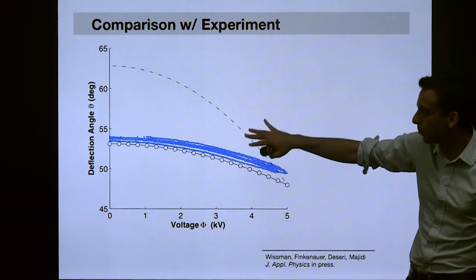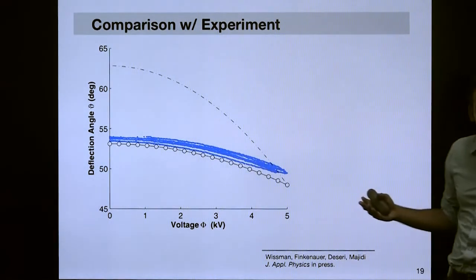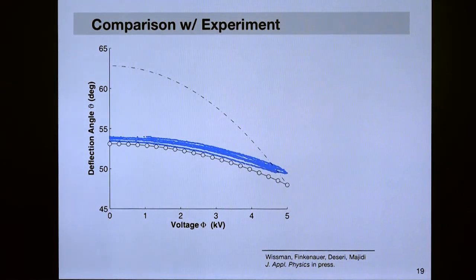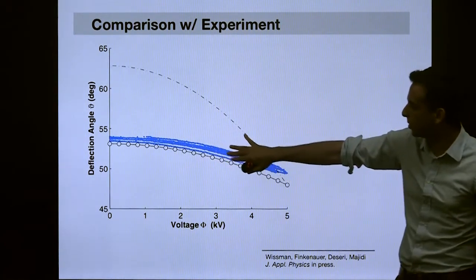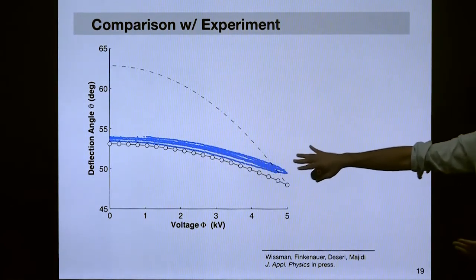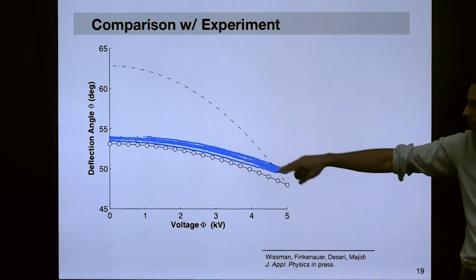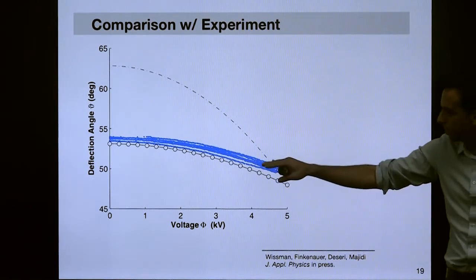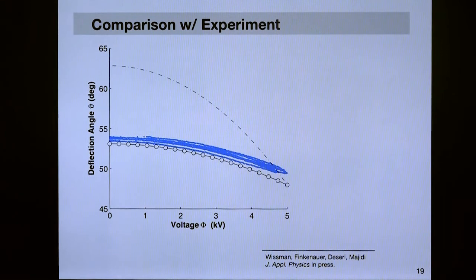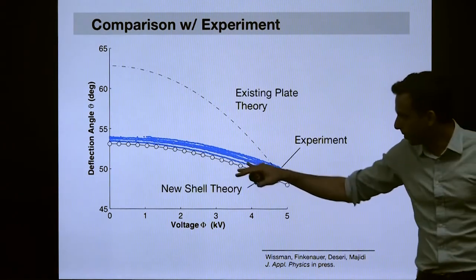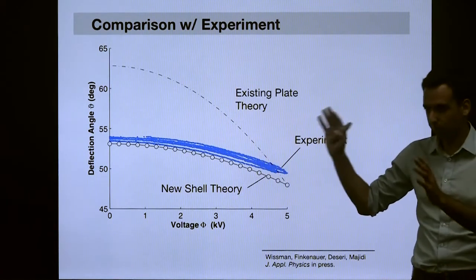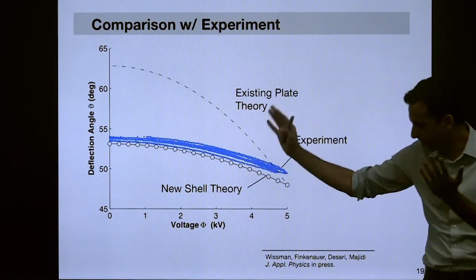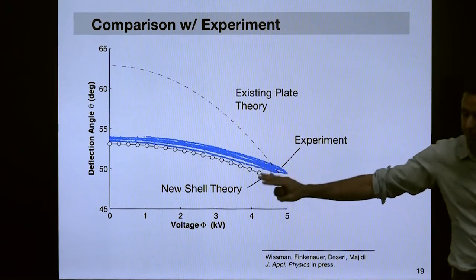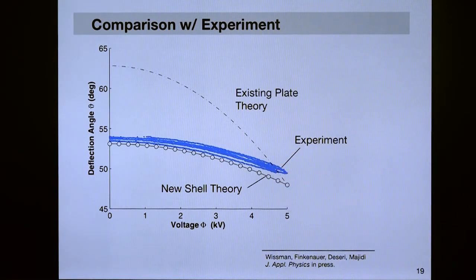But the important lesson here is that just from what we know about the dimensions during fabrication, the electric permittivity of these elastomers, and independent measurements of the shear modulus, we can make a priori predictions about what this coupling is going to be, and it's in much better agreement with our experimental results. This gives us encouragement that the principles of Maxwell's equations, variational techniques, and finite elasticity still apply to these classes of materials.